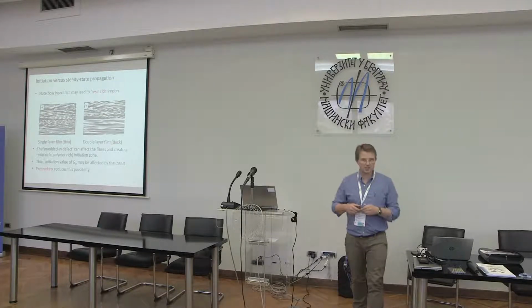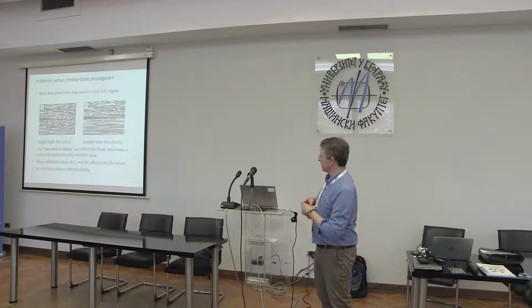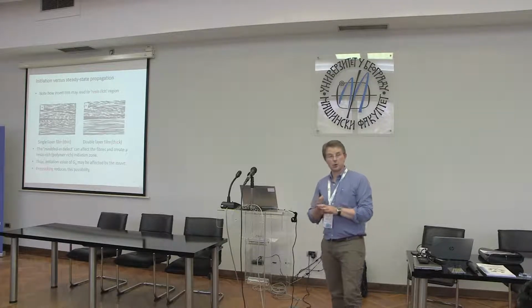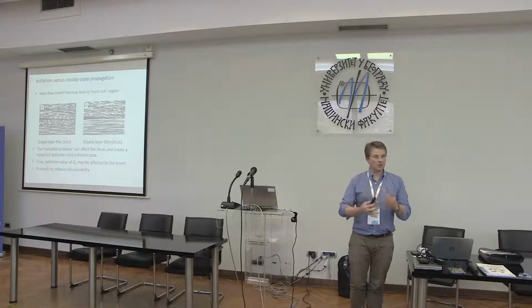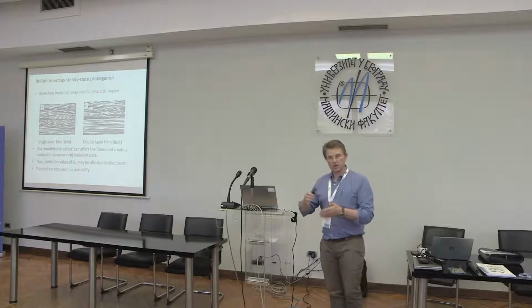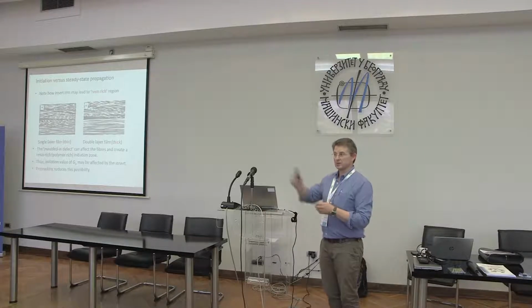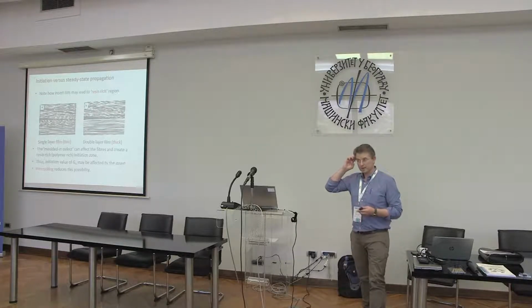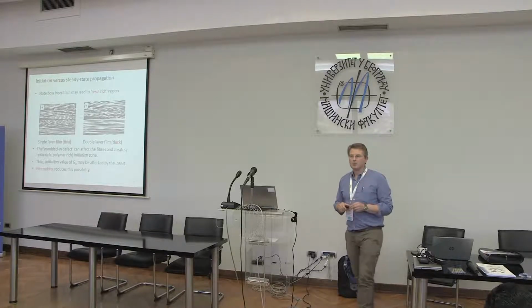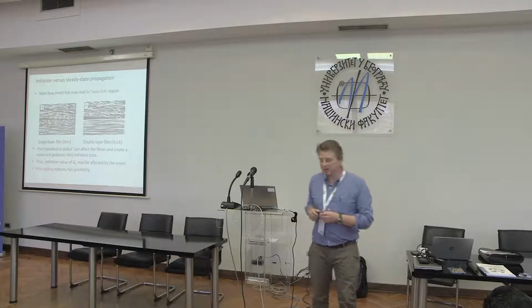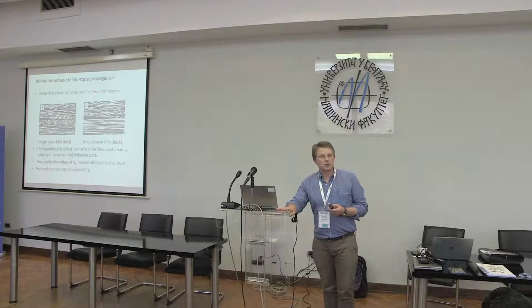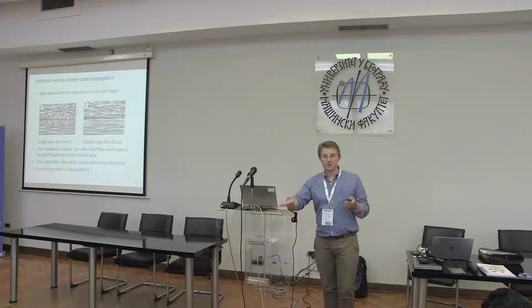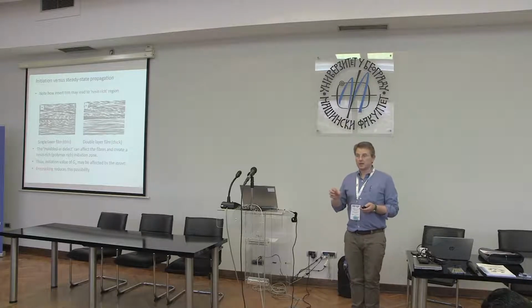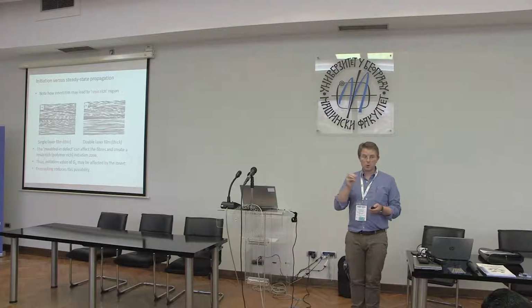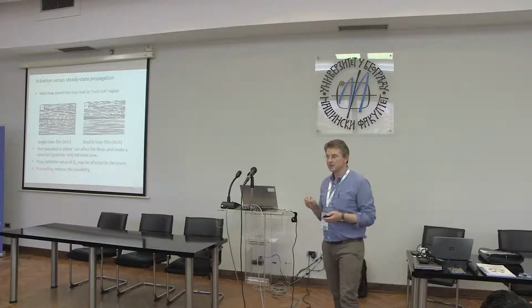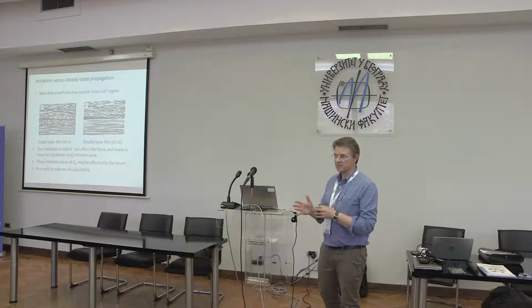So in the ESIS TC4 group, we've always had the philosophy that we're interested in crack initiation, but we're also interested in propagation. We want the full information about the experiment. We want to know how it initiates. We want to know how the fracture resistance changes as the crack grows. Okay? So we want that R curve. That's not necessarily universal. So if you take much of the work that was done in the US and the ASTM methodology, it was very much the case of the initiation is the only important point. The rest of it is subject to specimen dependence.